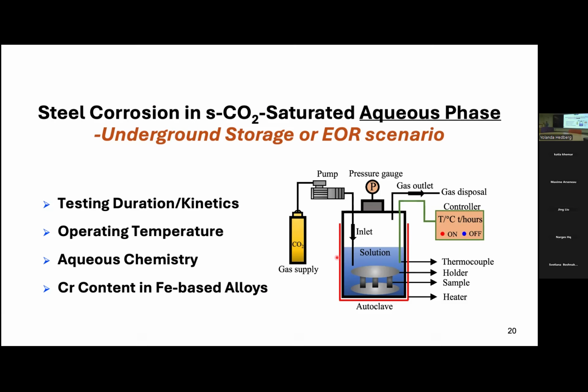Same for this one. Back 4 years ago, not many people had been working on this area. So the data I showed for this scenario is mainly from my group. We did work on different testing duration, temperature, aqueous chemistry, and also chromium level, as you could tell. We soak the sample in the water-rich phase, it will be more aggressive than the other one, right? So we're not looking at the pipeline anymore. We should have introduced some chromium contents into the steel to try to be more protective.